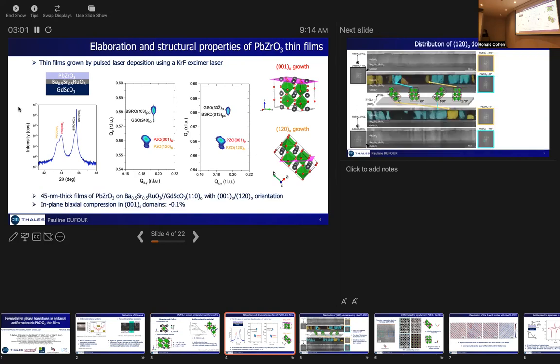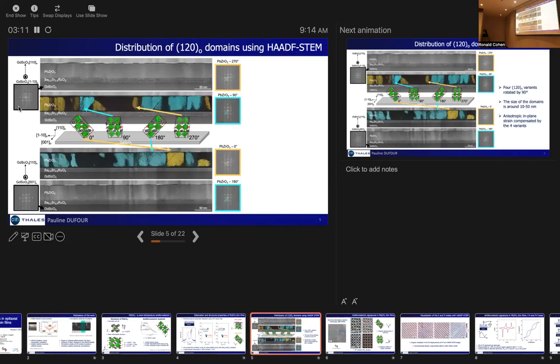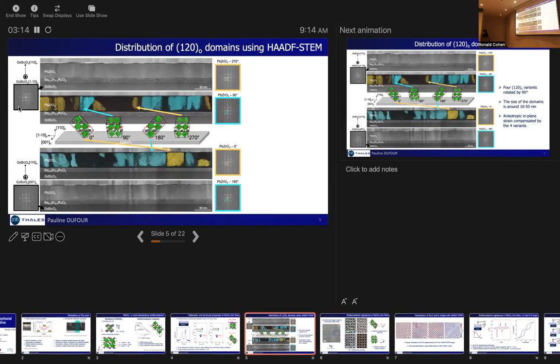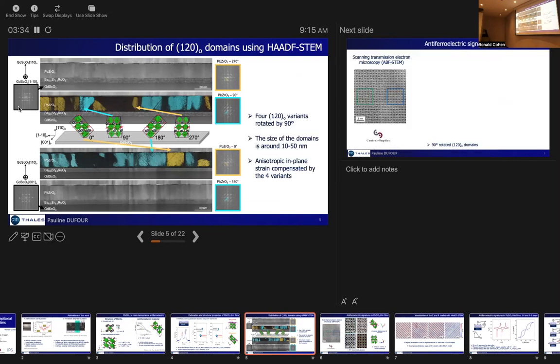For the 001 domain, we could extract an in-plane biaxial compressive strain of -0.01%, whereas for the 120 domain, it's a bit more complicated as STEM measurements reveal that we actually have four different variants rotated by 90 degrees. So basically, we imaged several STEM images along two different zone axes. And we highlighted the distribution of the different domains that are colored here in blue and yellow. Interestingly, the size of these domains is from 10 to 50 nanometers.